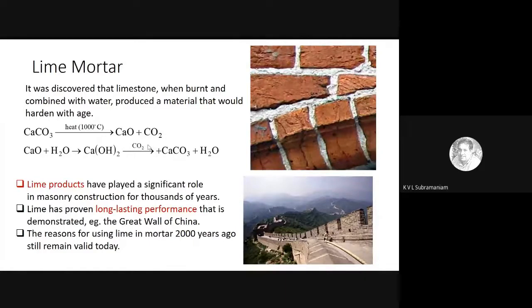And this material has been used extensively in structures that have lasted forever, including all of our historic monuments that we see in India, the Great Wall of China, which has been in existence for 2000 years. So it's a very good material. And the interesting thing about this is that it gains strength as we go along. The reaction of calcium hydroxide converting to calcium carbonate is a slow reaction, and it takes a long time to complete. So even as we speak, even the 2000-year-old structures are still gaining strength because this conversion process is still on.